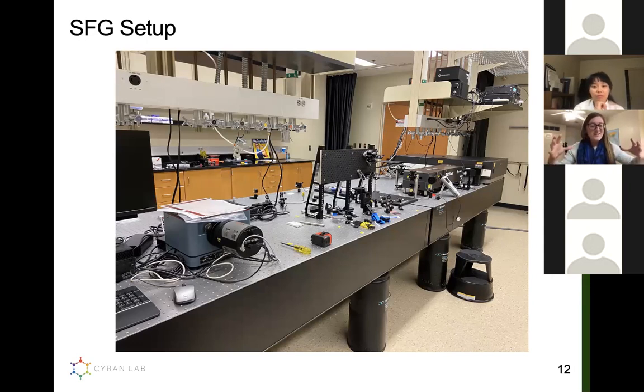So the spectrometer itself is not very condensed in this case, but in order to generate these pulses that we need, so this visible pulse and this IR pulse, we use a laser system here, and then we build up using different optical components in order to generate an SFG spectrum. And then after we generate the SFG, we collect it on a CCD camera. I am very excited to say that 2 weeks ago, we generated SFG. And so we're very excited to get started looking at different interfaces from here. And so this is just an example of what the laser lab here at Baylor looks like. And obviously you can see it's quite large, a spectrometer compared to that of an FTIR.